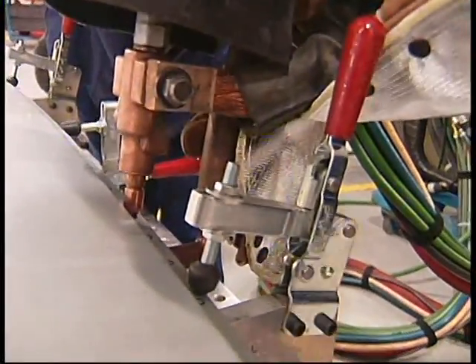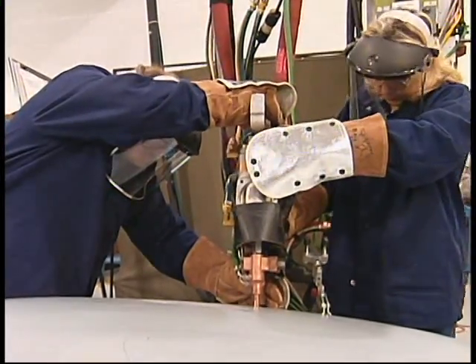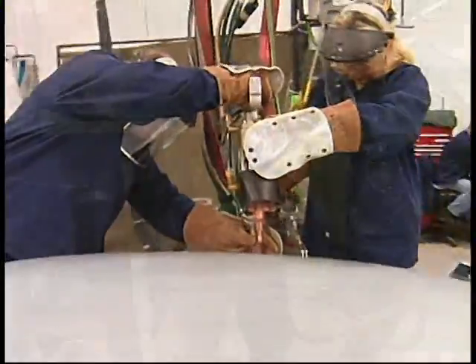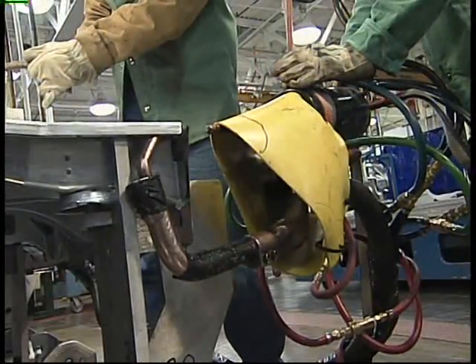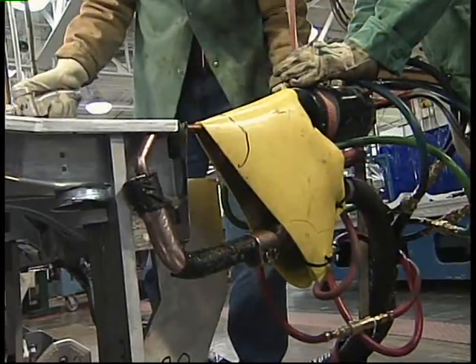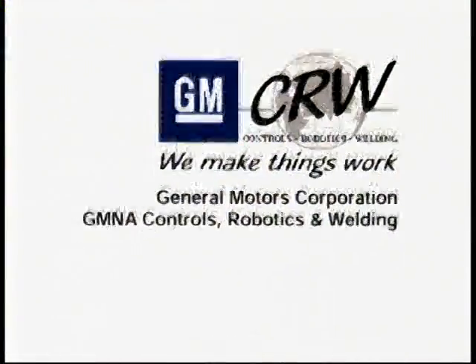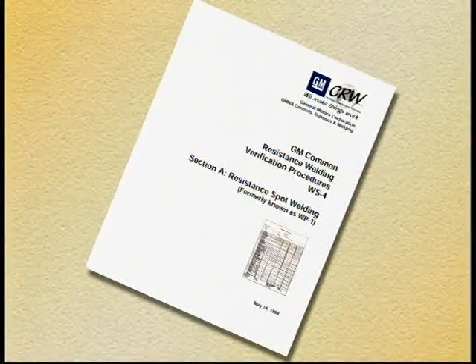At General Motors, we use a specific squeeze force setting which is dependent on material type and thickness. This value is a critical requirement for consistency in spot welding. You can find correct force parameters, along with weld time and weld current values, in the WS-4 specification.